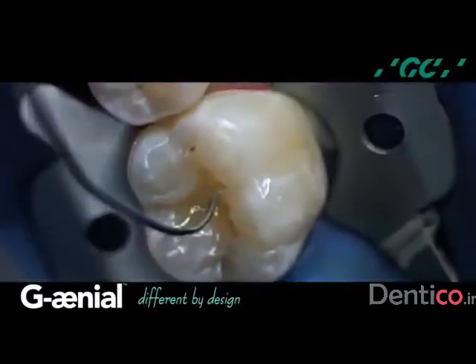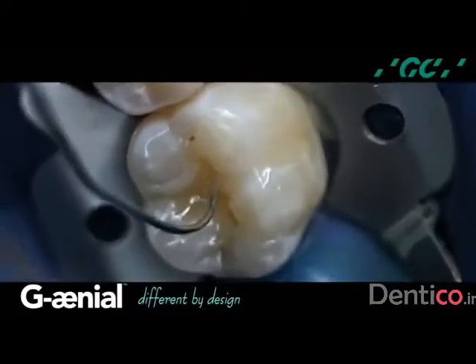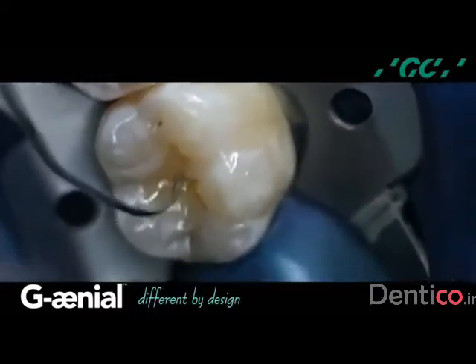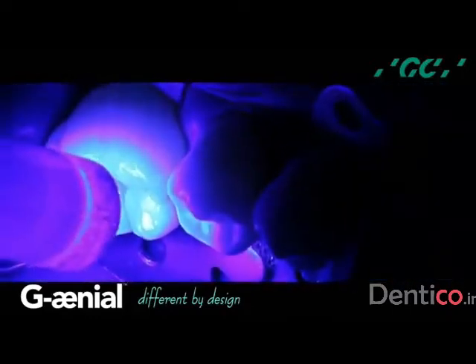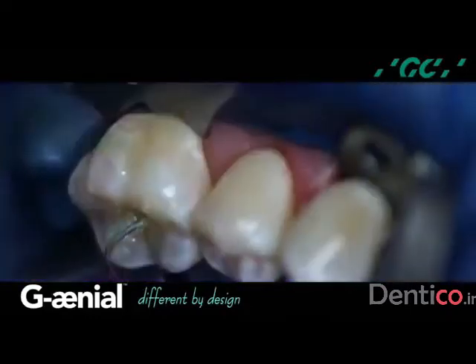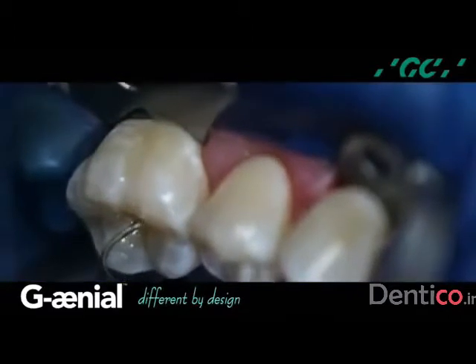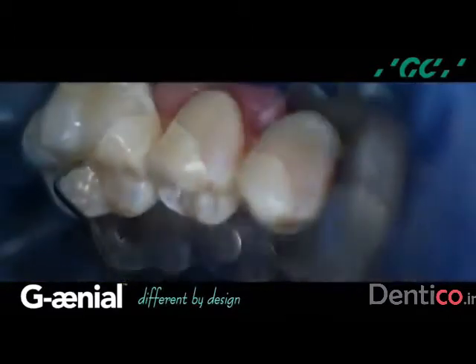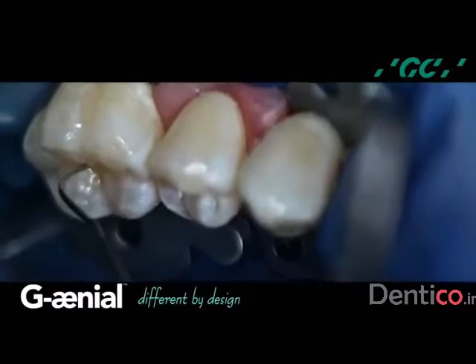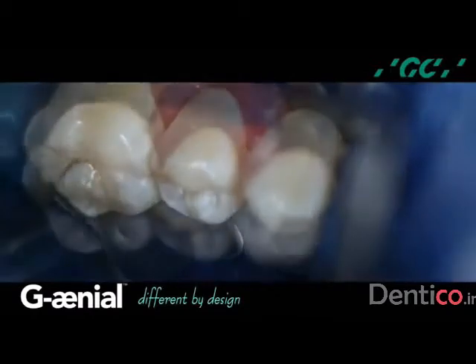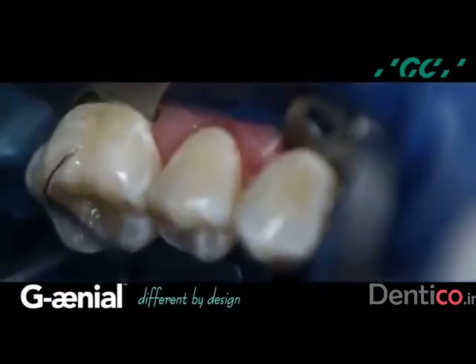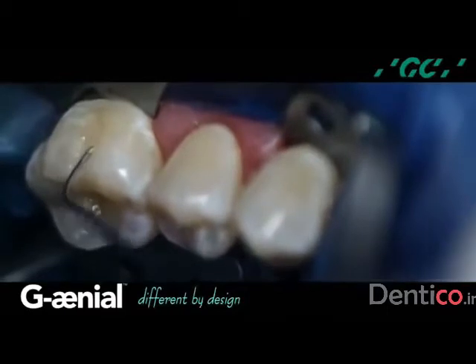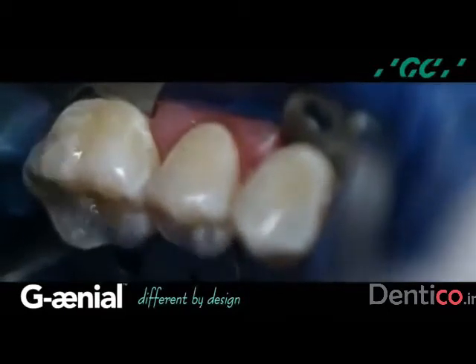Notice as I make the ridges, inclines, and planes, the material is easy to manipulate and sculpt, and each time I stabilize by light curing for 10 seconds. I continue to develop the anatomical form, placing increments of flowable and shaping with an explorer tip. A final enamel layer of flowable G-aenial Universal Flo is applied with an explorer tip to the buccal surface